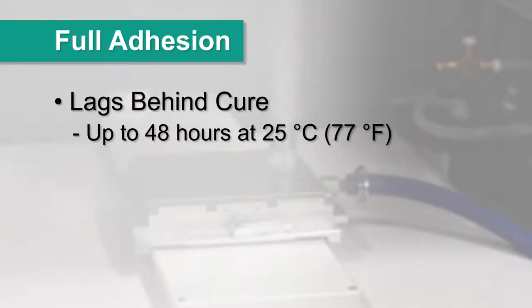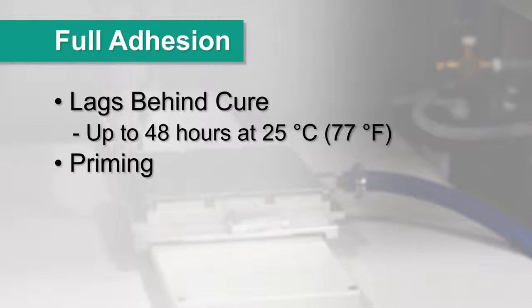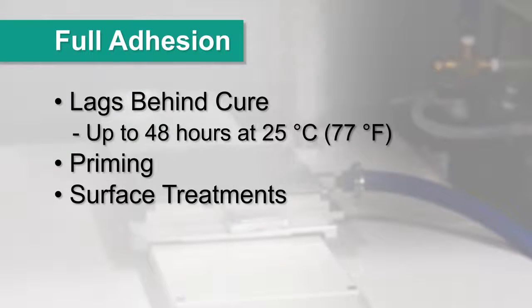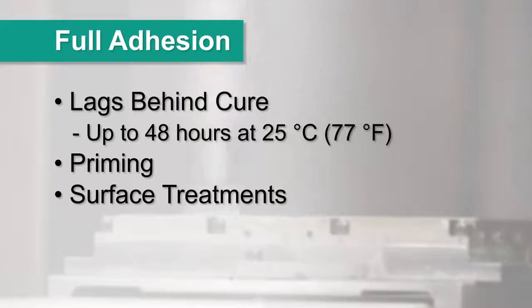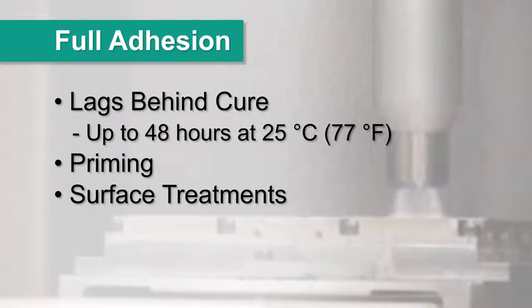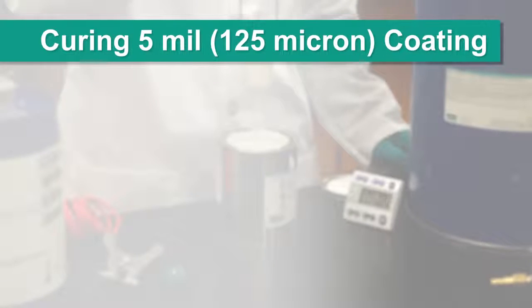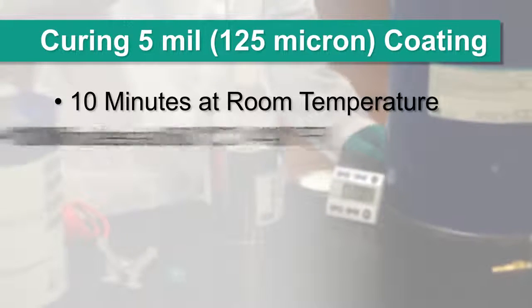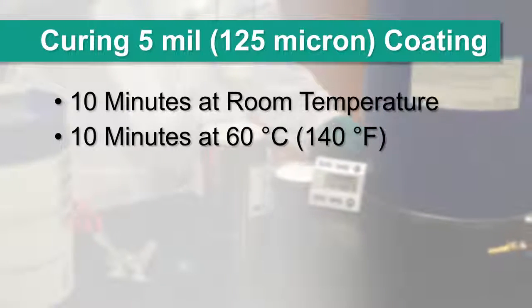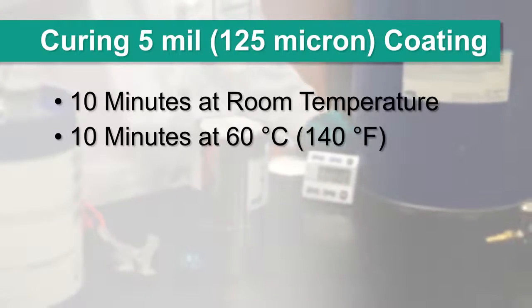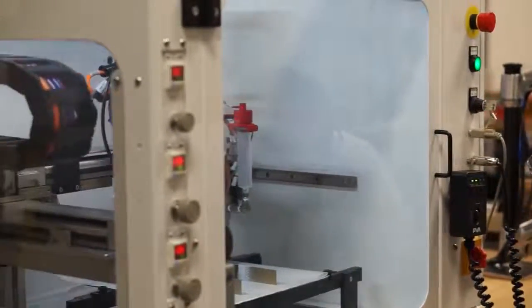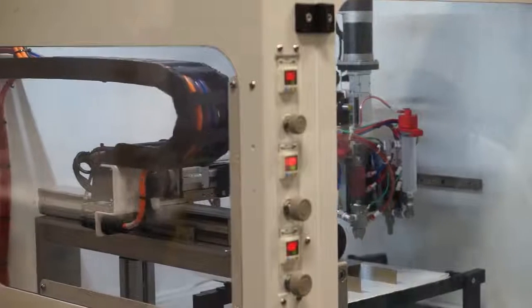On certain difficult, low surface energy substrates, you may improve adhesion by priming or with special surface treatments such as chemical or plasma etching. A typical cure for a 5 mil coating is 10 minutes at room temperature, followed by 10 minutes at 60 degrees Celsius. And you should never cure coating at temperatures above 60 degrees Celsius.